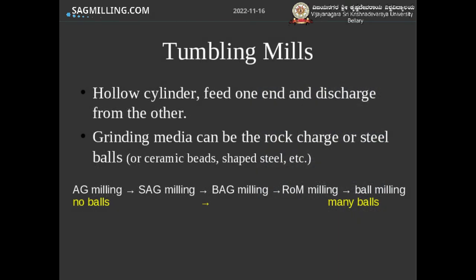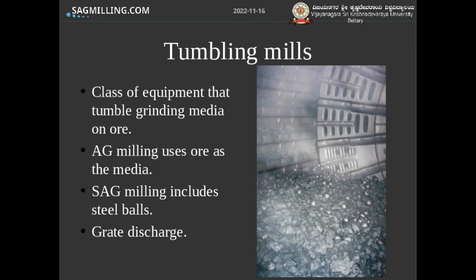There is a continuum of these mill types in terms of how many balls you find in the charge. Autogenous mills have no balls — it's basically rocks breaking other rocks. Ball mills contain basically just balls with a few fine rocks in the interstitial space between them. SAG mills have a rock-continuous charge with balls interspersed among the rock charge. And then there's an intermediate state between SAG milling and ball milling called BAG milling — barely autogenous grinding — where you've got a lot more balls and less of the coarse charge doing autogenous ore-on-ore breakage.